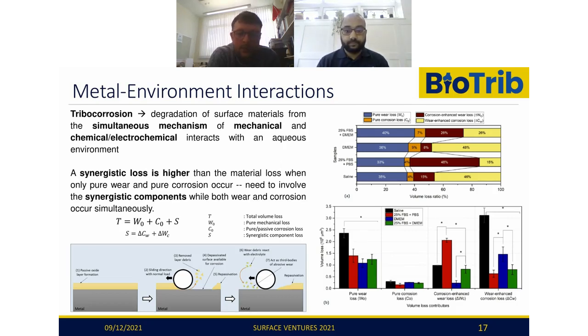What we find is that we get polymer. I don't want to use the word polymer brush because it implies that your polymers are all extending from the surface due to steric repulsion. I think what we've got is polymer brush systems which then become entangled, so it's more like an entangled gel network rather than a polymer brush system, depending on the grafting densities, which depends on how long you do it for. But essentially these things will graft to the surface of as ground stainless steels, and under dry conditions, they reduce the roughness of those surfaces.